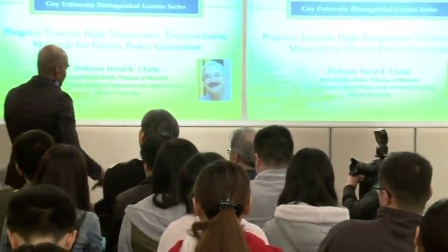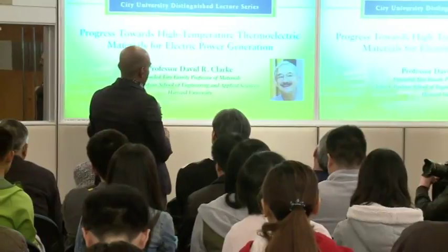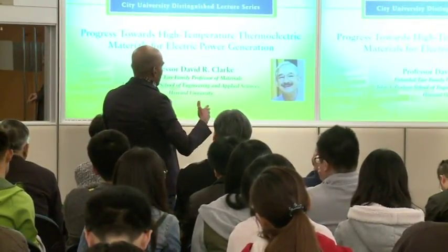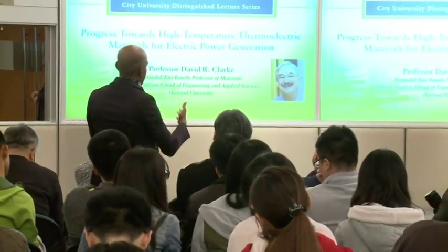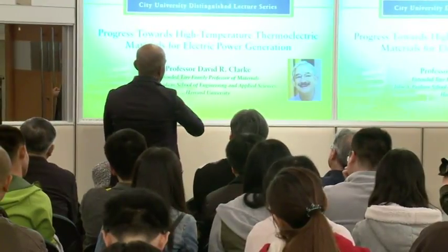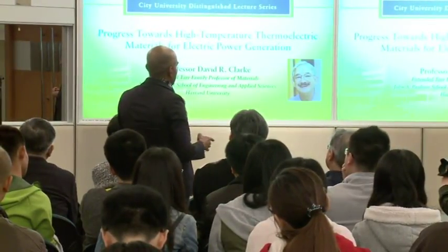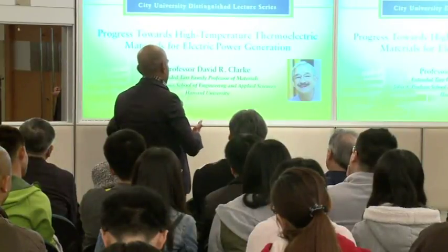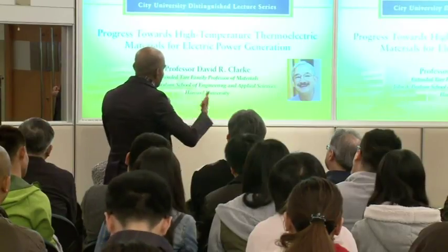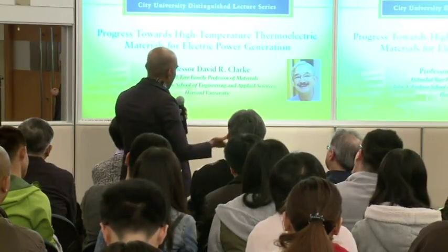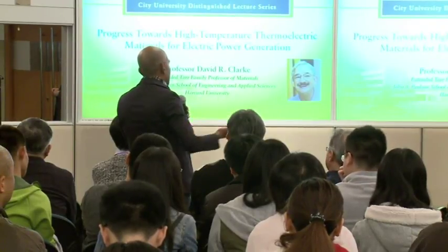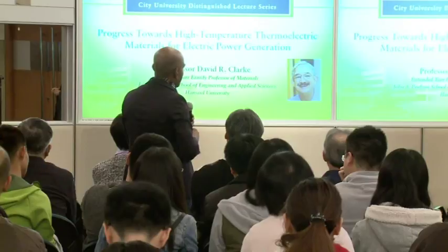Okay, so regarding the indium oxide, zinc oxide superlattices, you can reduce the thermal conductivity quite a lot. But as you know, ZT also depends on the electrical conductivity. Standard conventional materials like bismuth telluride almost behave like metals, with metallic conductivity. But when you talk about oxides, it's a really long way to go to enhance it because they're wide band gap, and even if you dope, it's not going to have a high electrical conductivity. So what do you think about this?